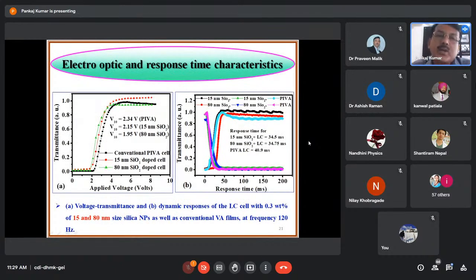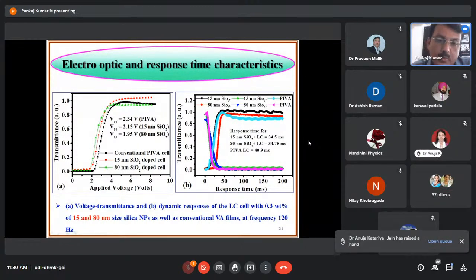So again, we are coming to the electro-optic and response time characteristics for these display cells. You can see in figure A, the conventional PIVA cell is the black dotted graph, the red one is the 15 nanometer silica doped cell, and the green one is the 80 nanometer silica doped cell. The threshold voltage is called V10. We generally show it with the help of V10. So V10 is 2.34 volt in case of the PIVA.